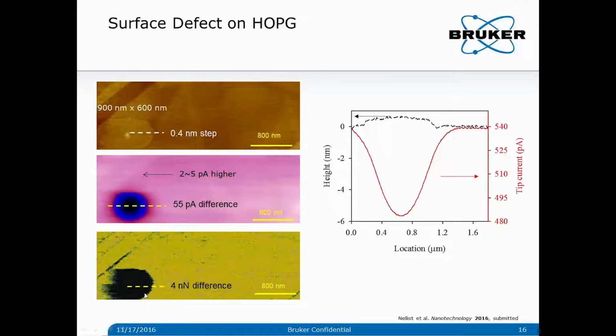Very interestingly, this region also has very different nanomechanics compared to the terrace. For example, the adhesion force is about 4 nanonewtons less than that on the terrace. So this is one of the examples of the multimodal imaging from the PeakForce SECM. You can get topography, electrochemistry, and also nanomechanics.